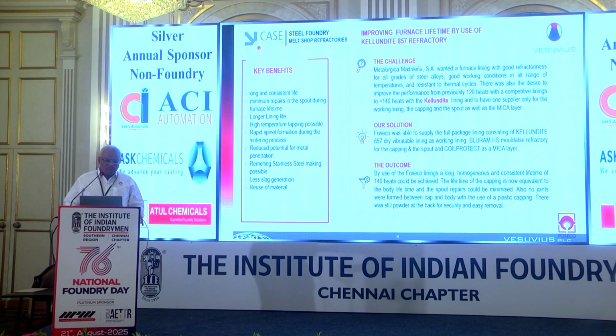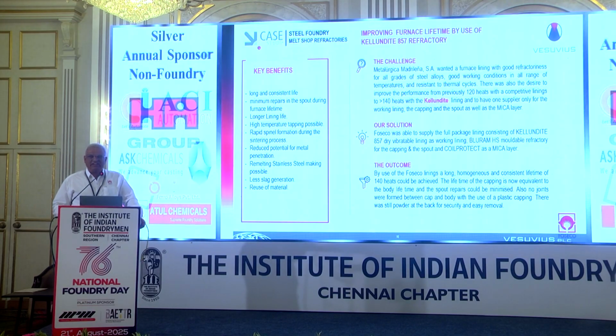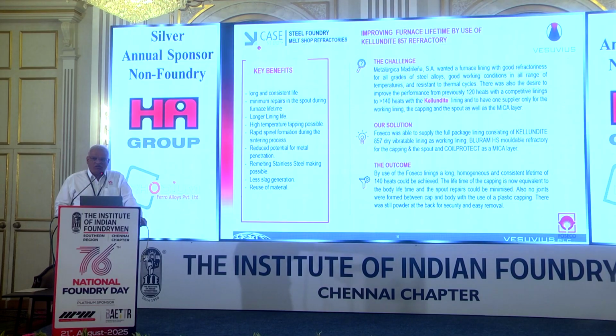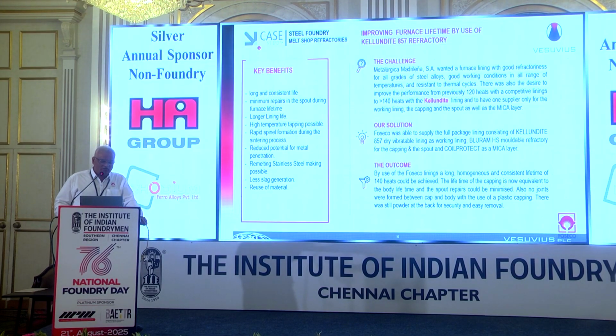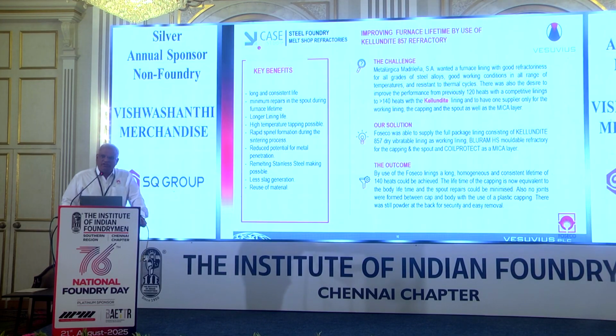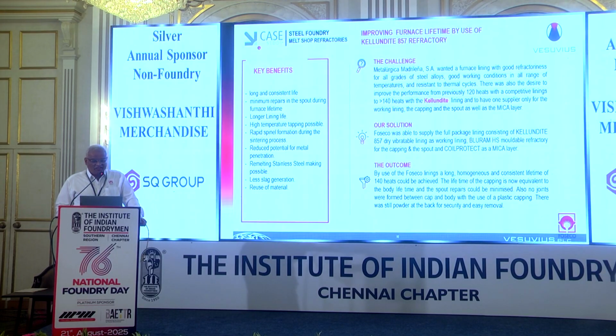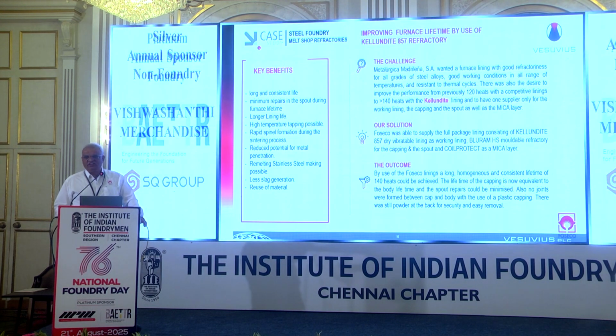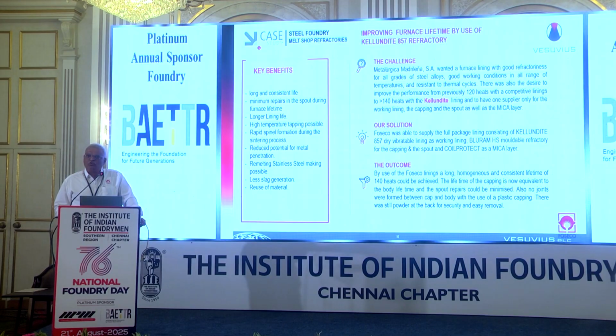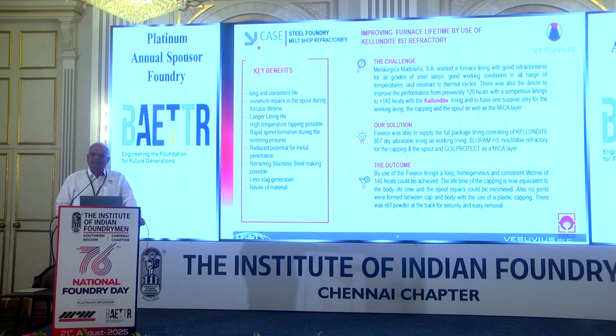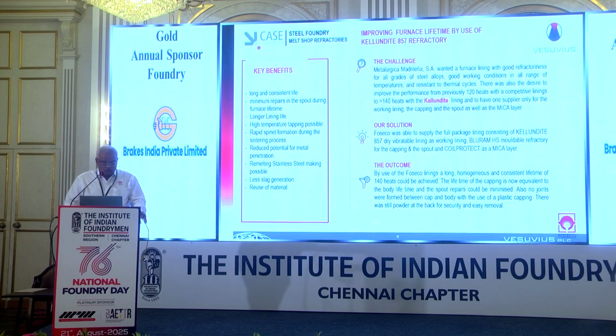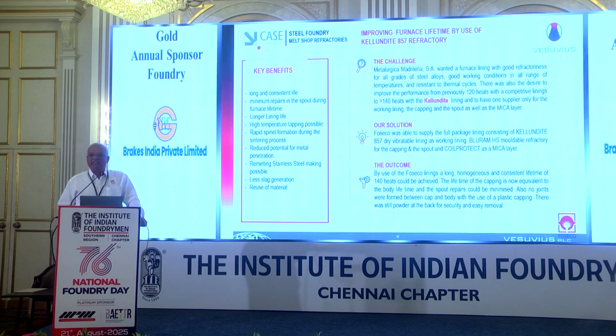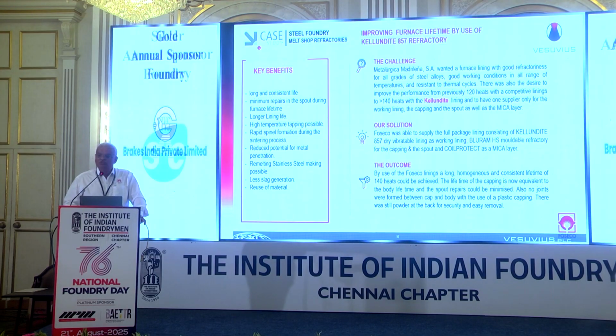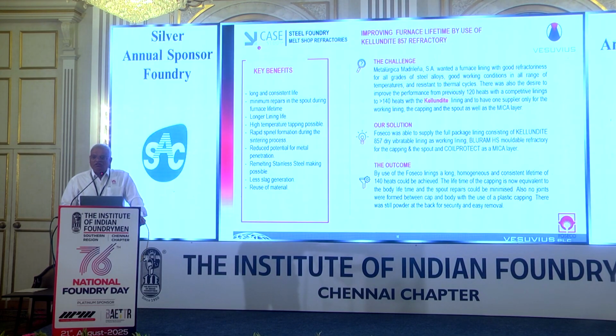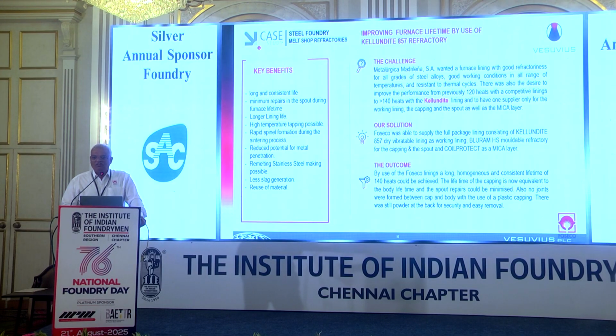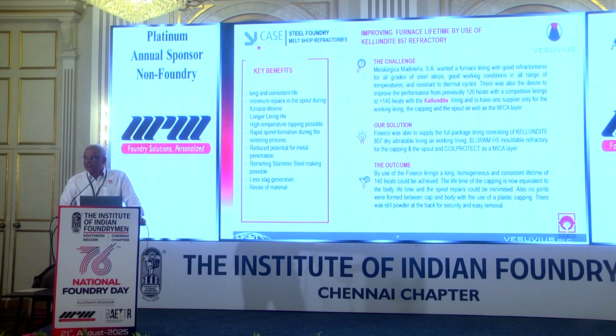So the benefits they got from this are long and consistent life, minimum repairs at spouts and top areas, and longer lining life. They are able to tap higher temperature materials as well as lower temperature materials. When they do the lining with Kellundite 857, they found rapid spinel formation. Then at the time of removal, they find a good amount of powder remains. That means the lining is in safe condition, and they can remove the lining quickly, and that material they can reuse also. So with this they got one supplier giving them all the products together, and the improvement they wanted in their furnace lining life was also achieved.